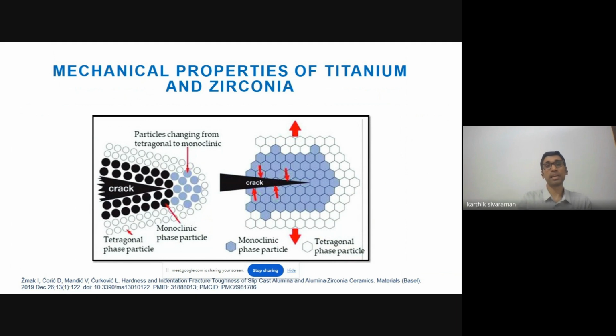Initially, when we were using ceramic implants in dentistry, we were mainly using alumina, but they were removed due to poor mechanical properties. Zirconia in its pure crystal phase has three phases: monoclinic, tetragonal, and cubic. The monoclinic phase exists up to a temperature of around 1170 degrees Celsius, the tetragonal up to around 2300 degrees Celsius, and cubic above 2300 degrees Celsius. When there is a transformation from the tetragonal to the monoclinic phase upon cooling, a volume expansion is seen, and there is propagation of cracks, which can result in adverse mechanical properties of zirconia.